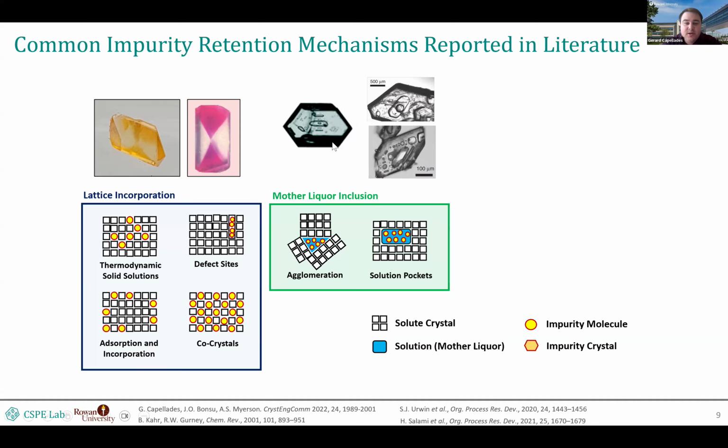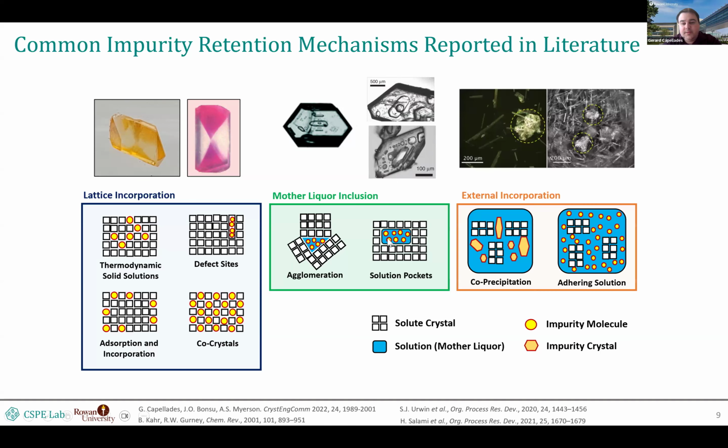So you can have examples of solution pockets that are formed inside growing crystals. Those are fairly rare. We're going to discuss that in a moment, right? But you can have solution pockets, and of course, if your mother liquor contains all those impurities, the crystal will end up containing that, right? And same goes with things like agglomeration, right? You start agglomerating all those crystals. You make hard-bound agglomerates where the wash solvent is not able to penetrate within, and you end up having some other liquid that's trapped in there that basically contributes to the impurity levels in your powder, right?